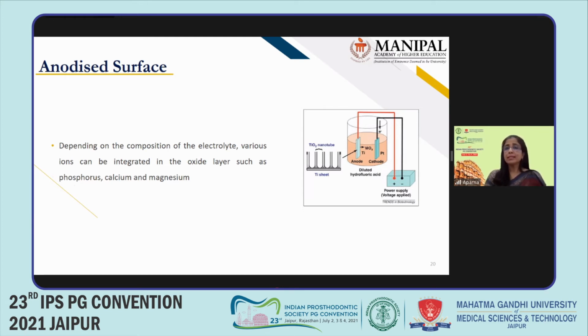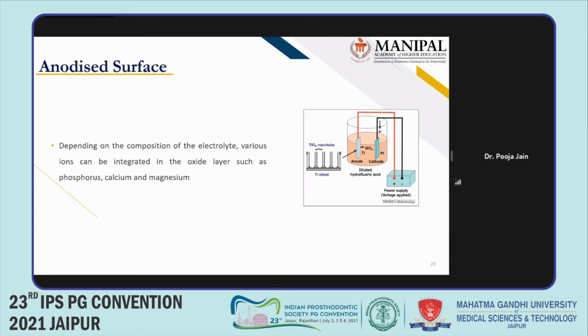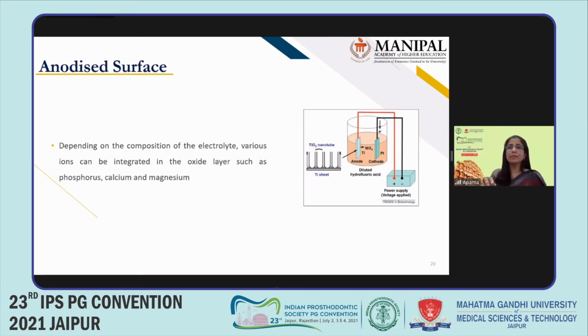So when implants are placed in the electrolyte solution, what happens is at a lower voltage, which is below the dielectric breakpoint, you get a constant oxide going over it, okay? But when the voltage is increased, there is an increased gas evolution. There is basically bubbling that happens, making the surface oxide very porous. So the pores that you see on the anodized surface are typically because of the increased gas evolution, because of the bubbling that has happened, because the manufacturer has increased the voltage there, right?